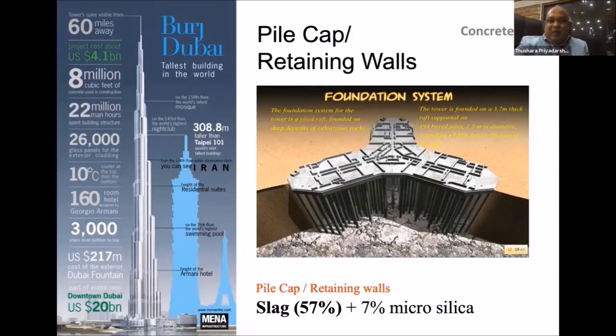So probably some of you are aware, or this may be the first time that you are aware of this type of mix: 57% of slag, 7% of microsilica, meaning 64% of cement replacement with some other material. I'm sure most of you like ordinary Portland cement. So here we are replacing ordinary Portland cement, 57% with slag and 7% with microsilica. So whether this is good or bad, actually, for the Burj Khalifa they could easily have used ordinary Portland cement for this structure. They have enough money. Of course, they have invested a hell of a lot of money. But they have used 57% of slag because it is really good for high performance.